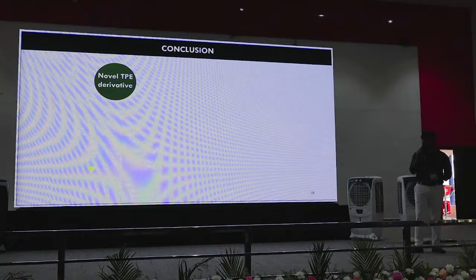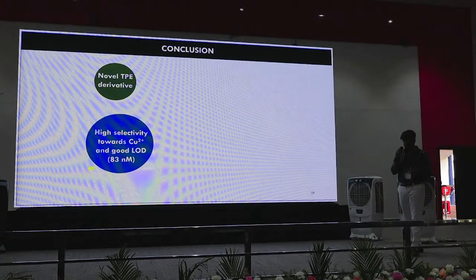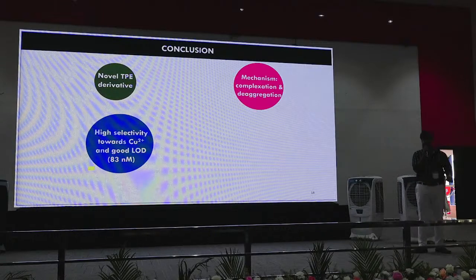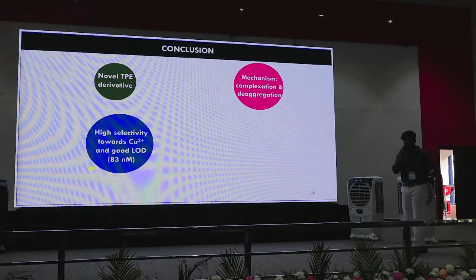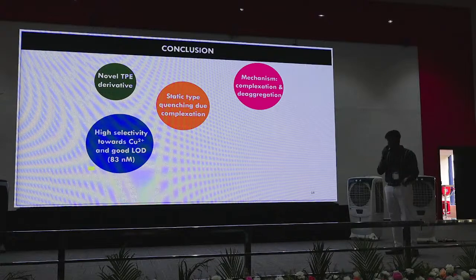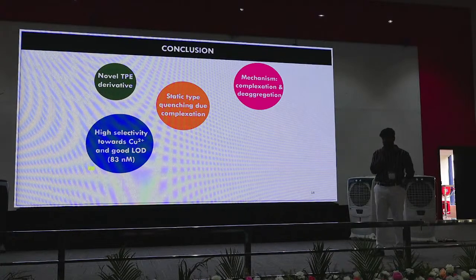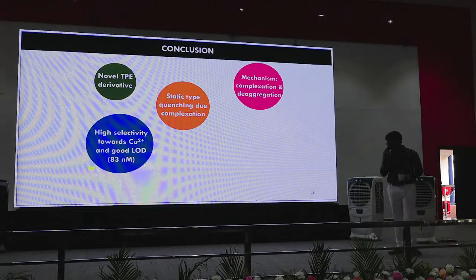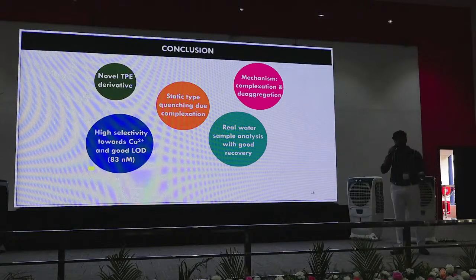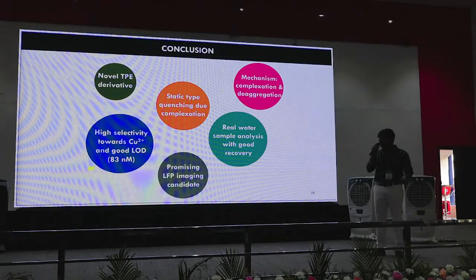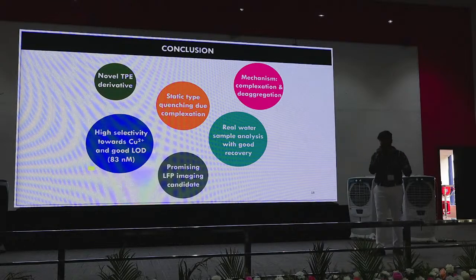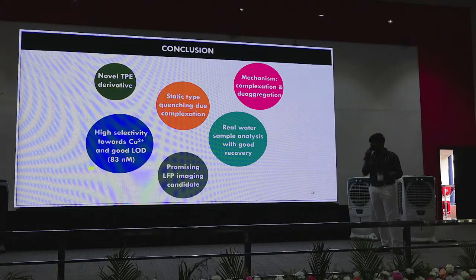And the conclusion is, we have developed a novel TPE derivative. It has good LOD and selectivity towards copper, and the mechanism is delineated to be complexation, deaggregation, and static quenching, which we found out from the TCSPC decay experiment. And we also did real-world practical applications with a good recovery rate. And finally, it is a promising candidate in LFP imaging.